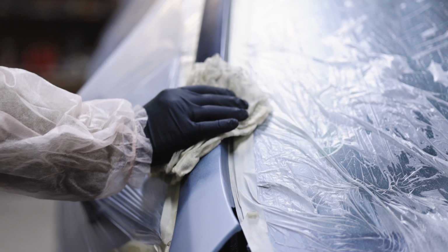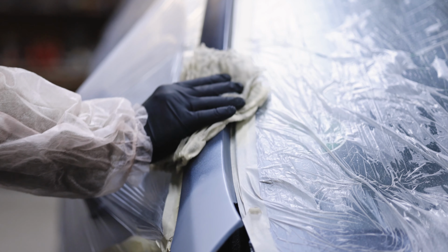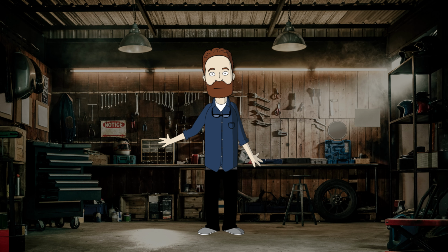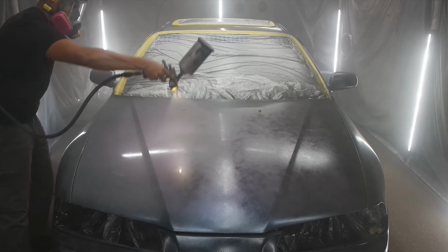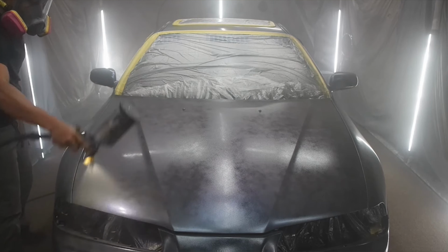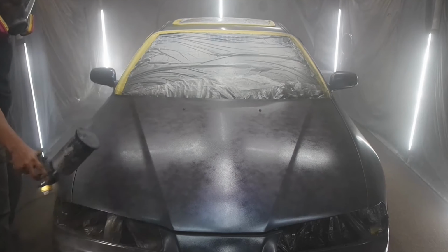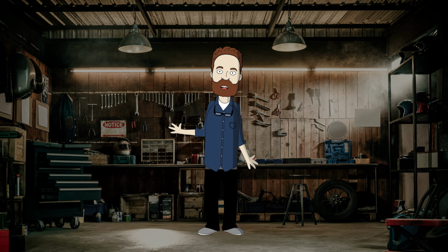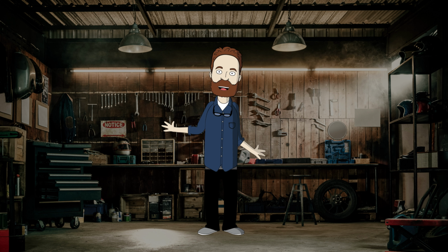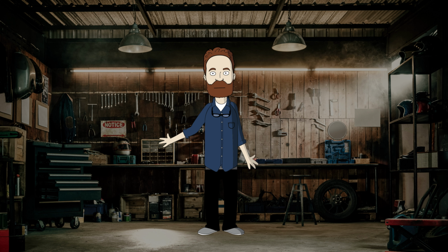The second step is removing or covering all the parts that are not going to be wrapped. Then, you move the car or parts to the paint cabin. Once it's done, you can start spraying specialized isolation primer for liquid TPU and letting it dry while keeping the necessary temperature in the cabin. It will help the wrap to bond properly and increase longevity, so the wrap will not slip off in 1 week, like Plasti Dip.